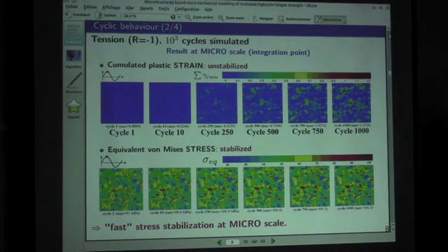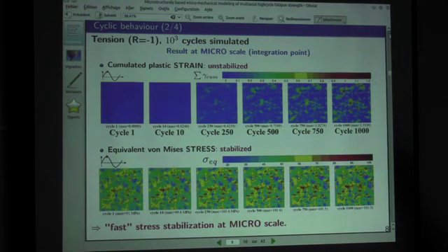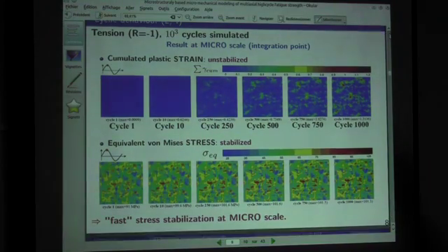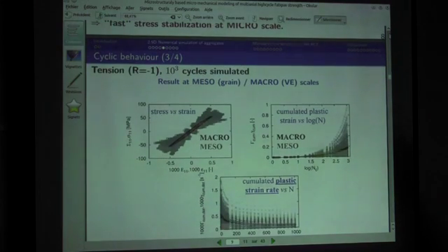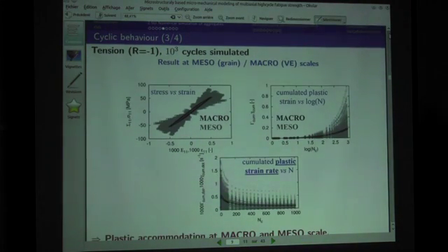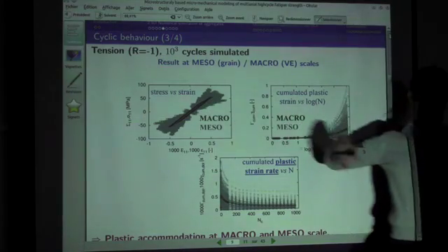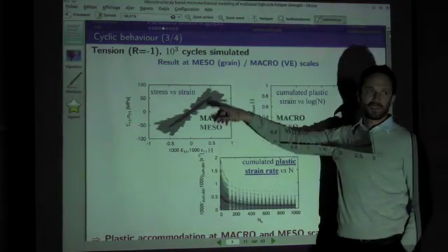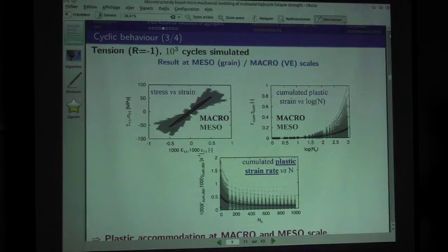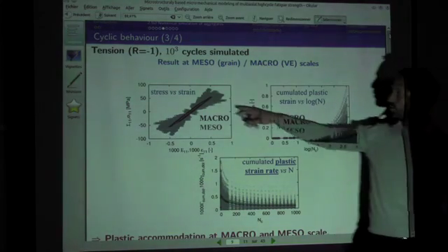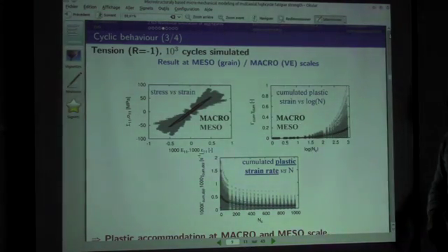So we have fast stress stabilization at the micro scale, at the meso scale, and with constant increase of the plastic strain. So we have plastic accommodation at the meso scale. You can see it more clearly here when you see the macro cyclic loading, and you have the meso response, and it's response of the grains. So you can see that the picture that you have is quite different at the macro and the meso scales. And when you analyze local behavior, you really widening your local response of the material with respect to the macro, the macroscopic applied stress. And if you look at the other quantities, more or less the same.